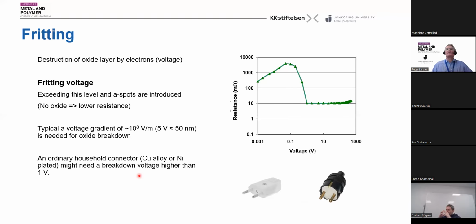And this is also illustrated on the curve. Here we have the contact resistance again in a logarithmic scale as a function of the voltage over the contact, also on a logarithmic scale. And at low voltages, the resistance is very high until you have the breakthrough voltage around 1 volt. And then it becomes constantly low for a big range of voltages.